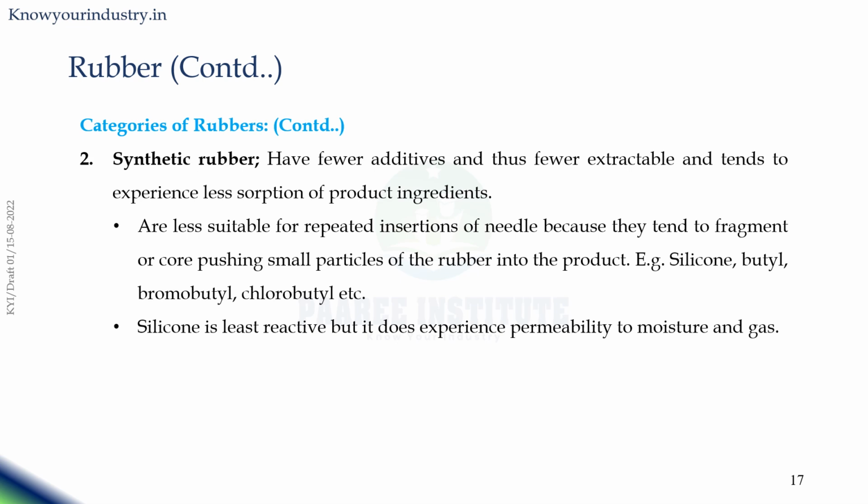These stoppers are widely used in injectables and are studied for quality controls such as non-volatile residues, a turbidity test on the extracts, pH change, and elemental impurities from the extracts, and certain known components are measured using LCMS techniques to understand the level of impurities on storage.